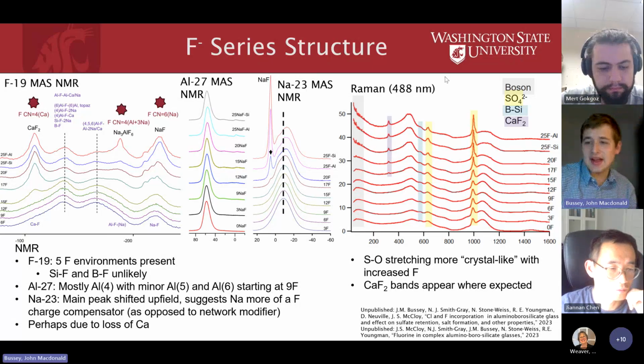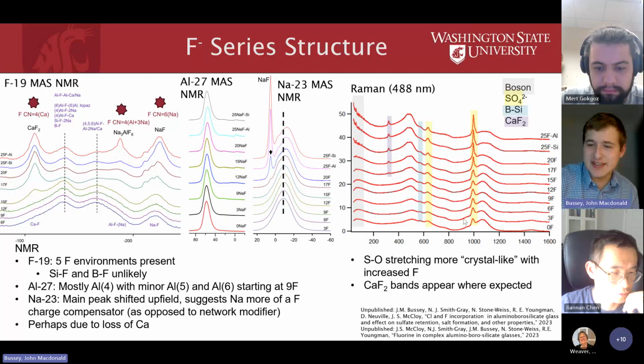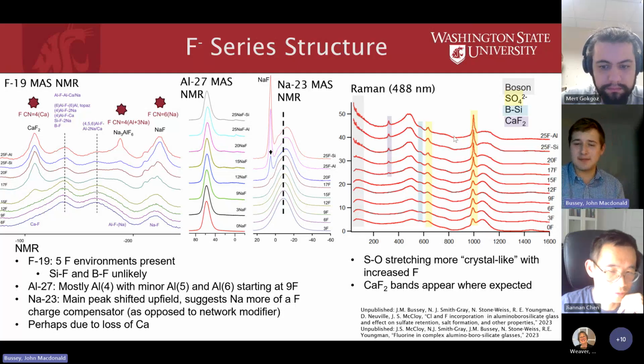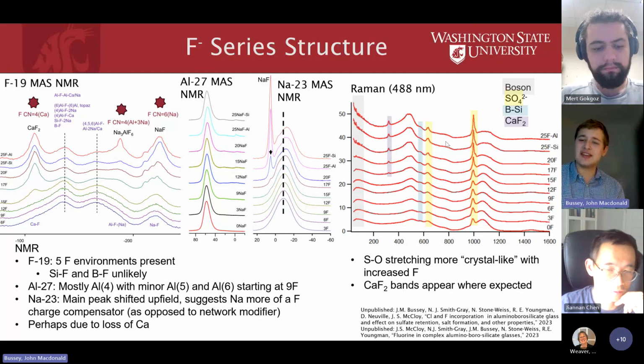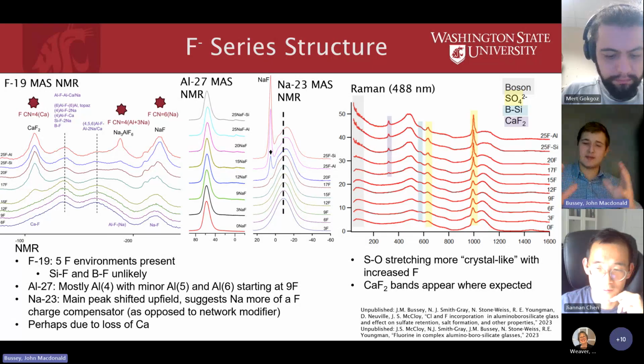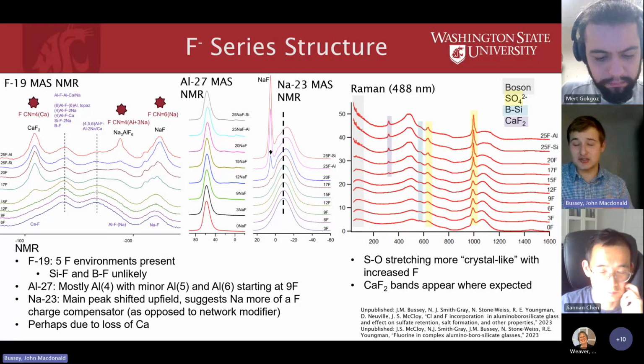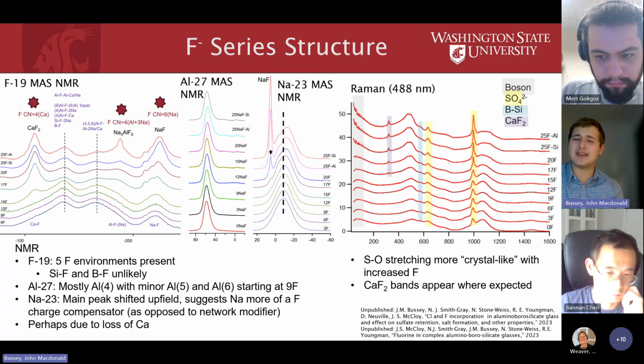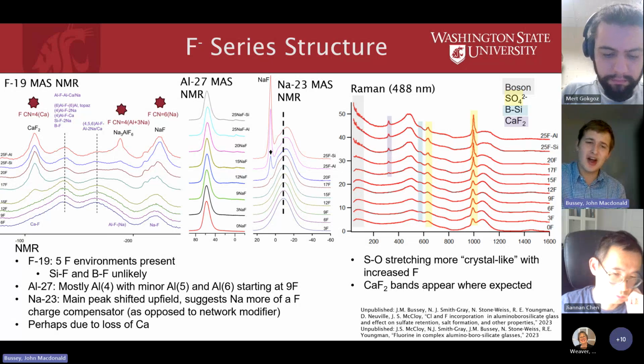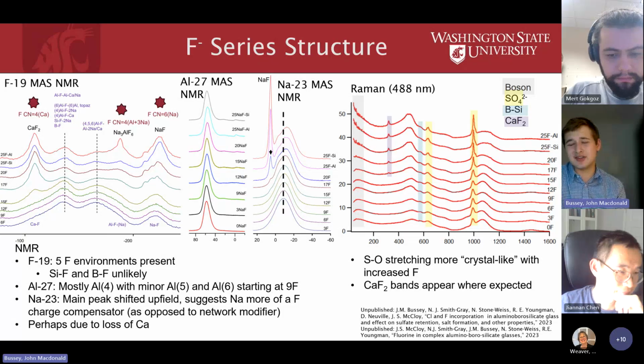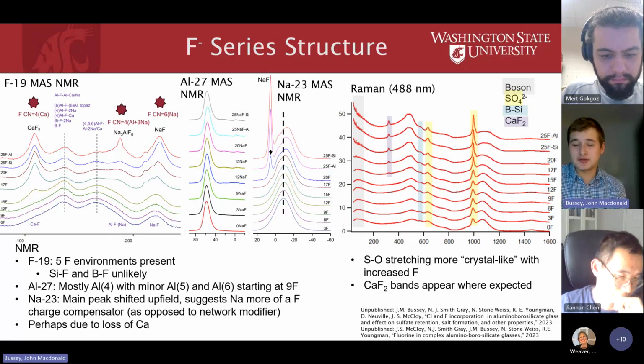We see that in the fluorine system we retain all of our sulfate, so that peak remains the same. However, you can see that the peak narrows quite a bit. Maybe it goes from a more Gaussian distribution to a more Lorentzian distribution, and that's maybe indicative of crystallization. So even though we can't see it with the X-ray diffraction, it looks like there's probably some crystalline sulfate forming, which is not ideal. That's not really what we want to find.